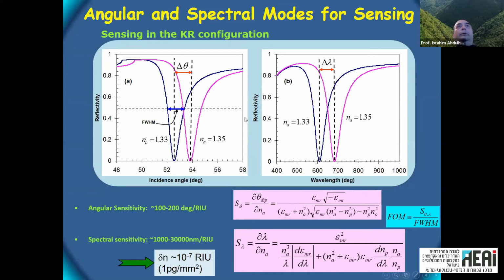This is a simple plot where you can easily plot reflectivity versus angle or versus wavelength. And you can even estimate the sensitivity analytically. The angular one looks like this, and the spectral one looks like this, which means giving something like, in this case, tens or 100 till 200 degrees per RIU. And the spectral one can arrive to a few tens of thousands of nanometers per RIU, even 50,000 sometimes.